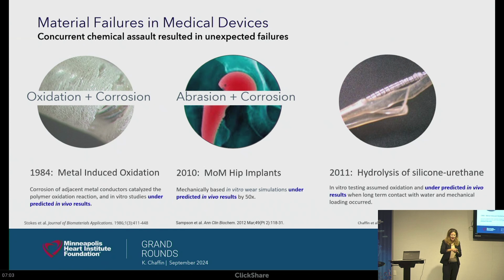If you do it fast enough in the laboratory, that corrosion doesn't have time to play a role in that combined effect. And again, hydrolysis of silicone, urethane materials, we were really, really trying to guard against this oxidation and this failure mode, and we forgot that both oxidation and hydrolysis play a role in vivo.